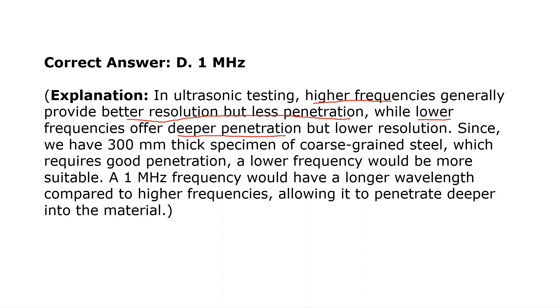The trade-off with low frequency is that you get the best penetration but the resolution will be low. Since we have a 300 mm thick specimen of coarse-grained steel requiring good penetration, we use the lower frequency — 1 megahertz.